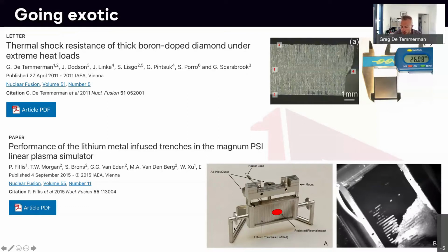And then people said, well, if one issue we have is that our metal is going to melt, why not use a liquid metal to start with? Then I don't have to worry about the shape and the melting, it's already melted. In that vein, people looked a lot at lithium because it melts at really low temperature. An advantage also is that because the liquid is flowing, you can use it to remove heat more efficiently. So you have more heat carrying capacity, and it's quite efficient. The problem is lithium is very reactive. For those who know, liquid lithium will just eat through copper like nothing. So in a nuclear facility, when you have water cooling everywhere, lithium reacts a lot with air and water, so it poses some issues.